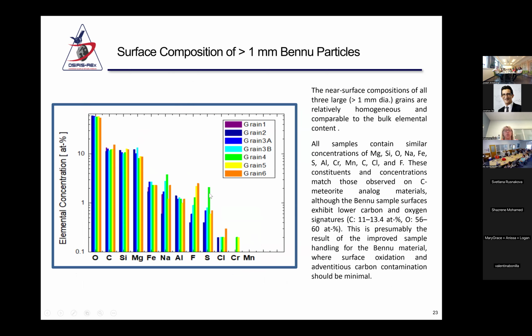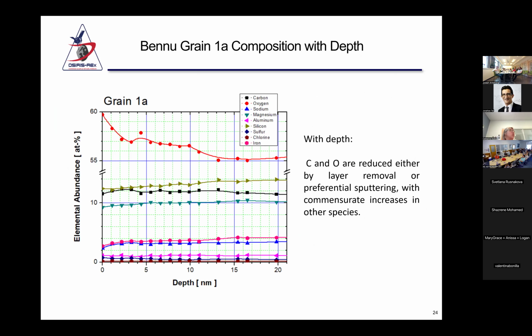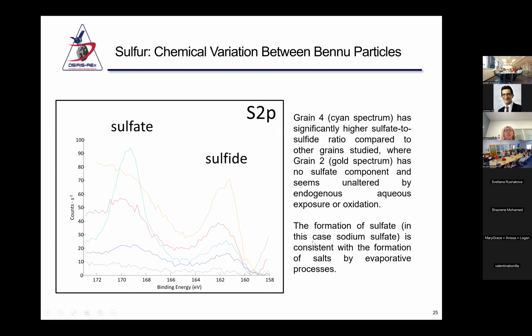Some particles have strong sulfur signals. There are a few where that's correlated with the sodium. We find that the near surface composition is generally homogeneous and comparable to the bulk content, except that they seem to contain lower carbon and oxygen than we had seen previously in meteoritic samples, probably due to the non-exposure to atmosphere. We've been looking at the composition as a function of depth, and then we'll be modeling this. We're also looking at the chemistry, changing the energy resolution constraints of our instrument.